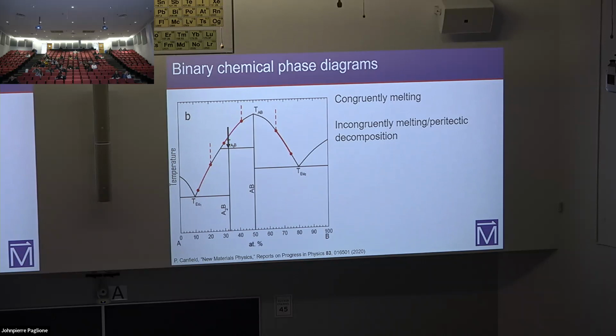A different way of putting this: let's come from the lower temperature part. If I take A and B in their solid forms, grind them up, and mix them together, I can heat at this temperature, and as long as I don't cross this decomposition line, sit around somewhere like here, and eventually they'll react through solid state reaction or diffusion to form this A2B phase. But that will only ever form a polycrystalline material, and it may take a very long time. But this was the route by which cuprates, for example, were originally developed, and it's useful in a lot of ways. So these are two distinct paths to producing compounds: congruently melting and incongruently melting.